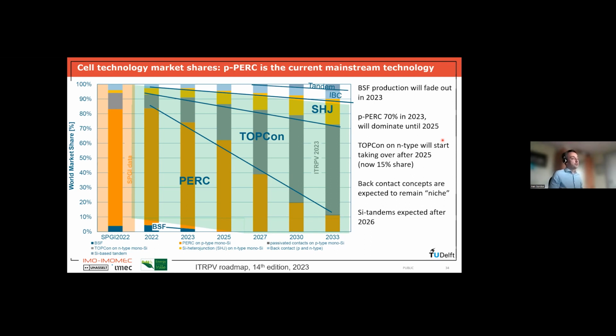What is the industry now producing? So if you look to 2022, we see that almost all cells that are being produced are this orange. So these are the P-type PERC cells. So P-type PERC is really dominating, is the main technology that is being produced at this moment. More than 70% of the market is P-type PERC. You still see here this dark blue, a few percent of back surface field. So aluminium back surface field has not completely disappeared yet, but after 2023, the industry predicts that it will completely fade out because efficiencies are too low. It's not cost efficient anymore.